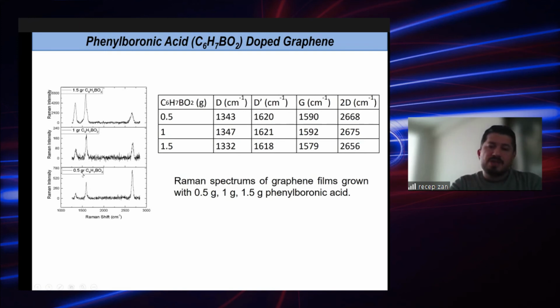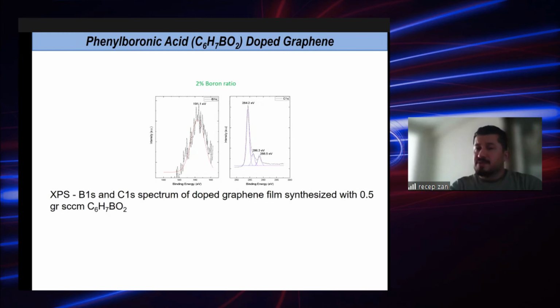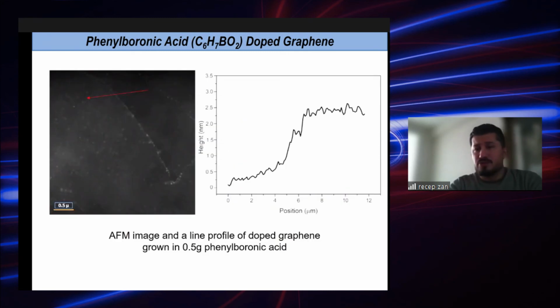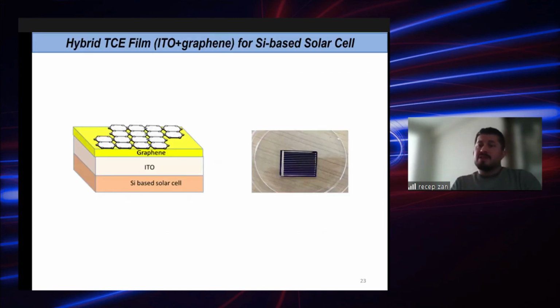So in our case, using 0.5, 1, or 1.5 gram, we were much more satisfied in terms of homogeneity using 0.5 gram. And once we have that, again, we check the XPS before we go to any AFM measurements. Again, we were happy to see the boron content and boron stability. 2% boron was found here. And the thickness was measured around 2 nanometer, which is a bit higher than the single layer, but we call it double layer.